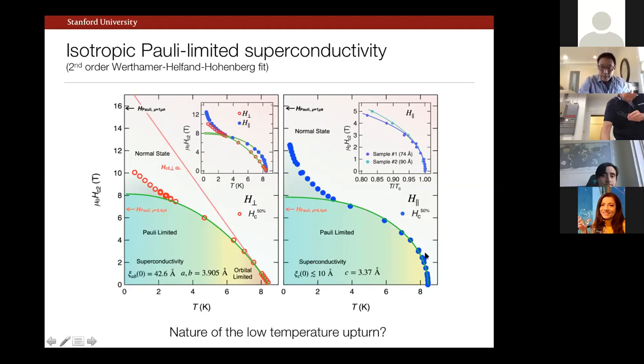And as I told you, if you take this square root as a measure of the susceptibility of the normal state, then this would give you the scale of the Pauli limit associated with this enhanced susceptibility. And it's quite reasonable in the sense that the basic HC2 fit extrapolates to that vicinity. It's a little bit higher because of spin-orbit coupling in the system, but nevertheless, this sets the scale. And of course, because we don't observe a region that is simply orbitally limited, we can only give a bound on the c-axis coherence length, unfortunately. We give, I can go into more details later, about a nanometer bound for that direction. So that's the main message, which is that we have a shockingly isotropic superconductor, and we believe that the Pauli limit is really governing that scale.